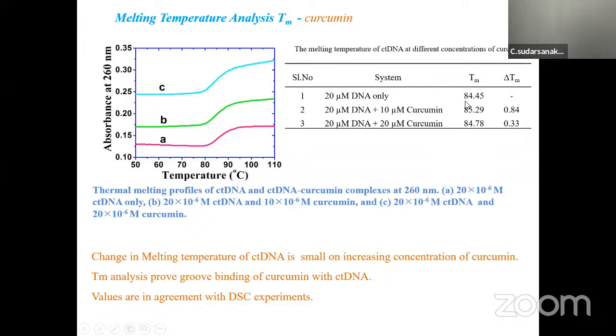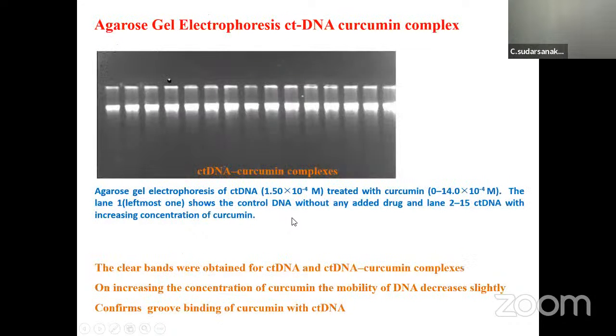If you look at the Tm value of 84.45, when you add 10 micromolar of curcumin, you find 85.29. If it is increased to 20 micromolar, it is only 84.78. It shows that, again, it's a groove binder. Again, you can calculate the binding constant. All those things you can do, but all this comes within the limit of experimental errors. All these different kinds of experiments agree with each other.